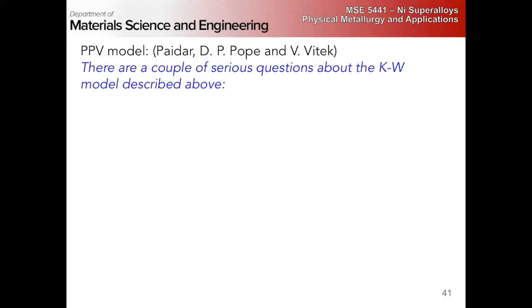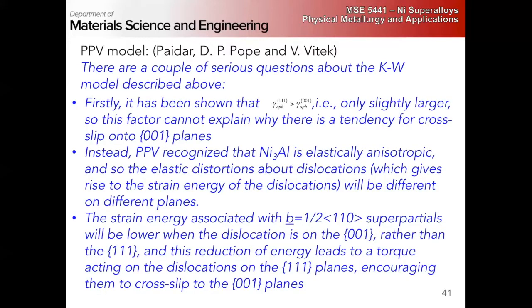It turns out it doesn't work nearly that nicely, right? People did a lot of experimental work and showed that the antiphase boundary energy on 111 isn't that much greater than on 100. And Kear and Wilsdorf essentially did all their calculations considering only isotropic dislocation interactions. If you actually take the anisotropy of the gamma prime phase into account, the interactions become a lot more complicated. The mathematics become much more difficult.